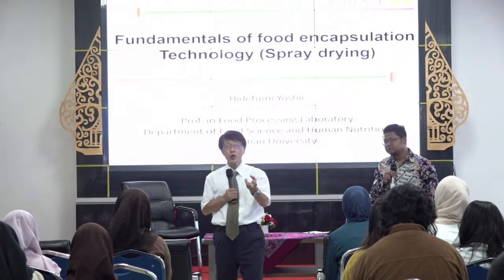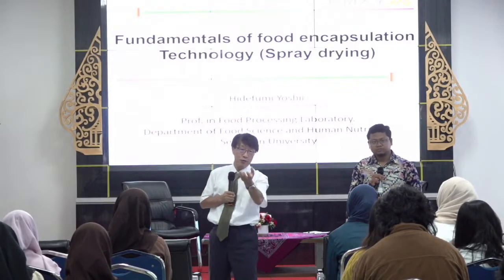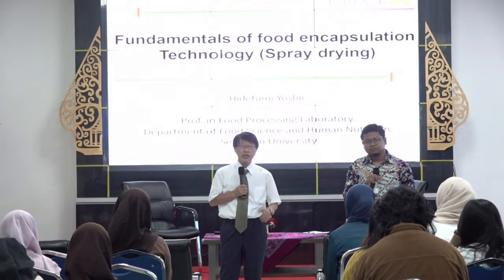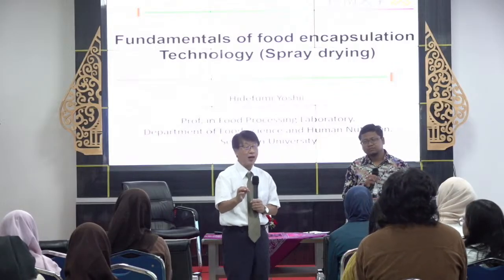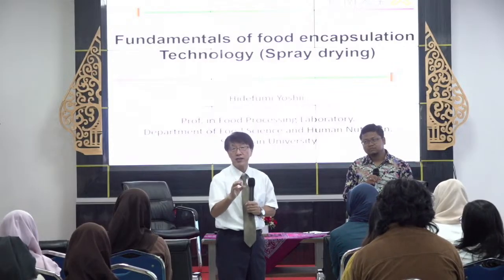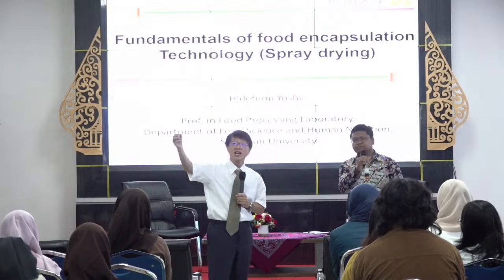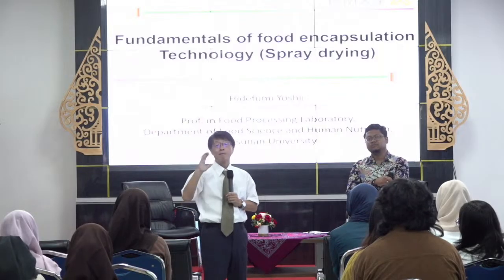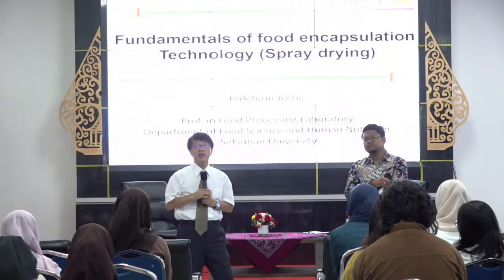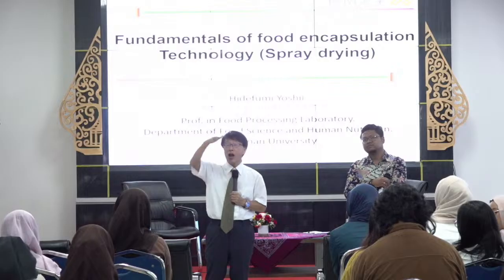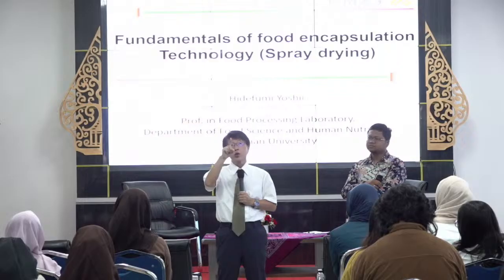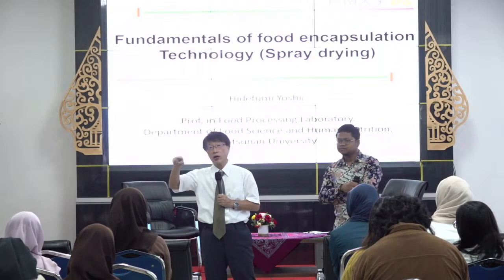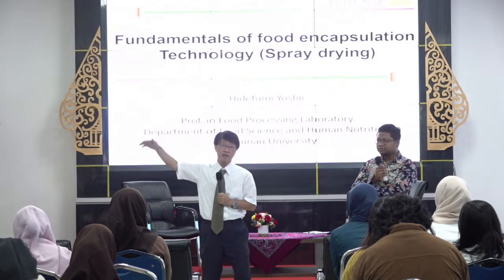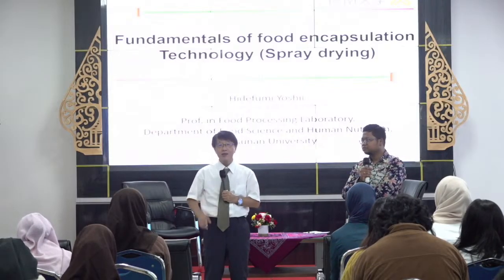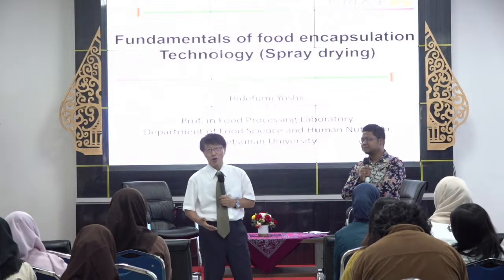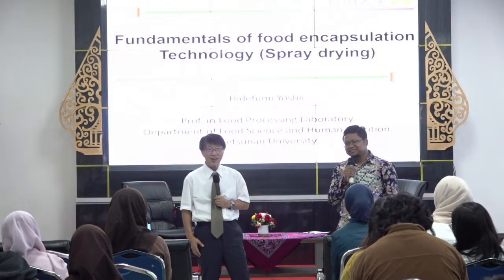But when we want a good powder, free flowing with good properties, maybe above 50 micrometers. With small oil droplet powder, the surface area of the powder is very high, so moisture absorption is very rapid. Therefore, in the food case, powder above 50 micrometers is better. So maybe the spray dryer size is 20 kilograms of water per hour evaporation ability. That is the industrial scale. Therefore, it is a very difficult question. So the powder size depends on the instrument, the spray dryer's type. Okay, it's okay? Thank you very much.